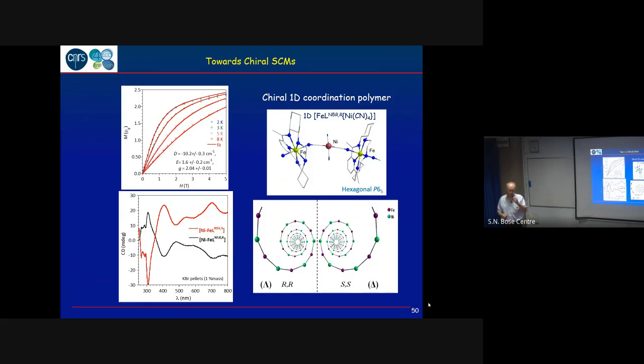But if you have hysteresis, how do you measure it? There is no hysteresis in M versus H. Because this is just one molecule, just one metal center, iron, and for such a species you do not block magnetization. You see, I can go down to 2 K. At this temperature, it's not blocked. Or you have to sweep the field very quickly.